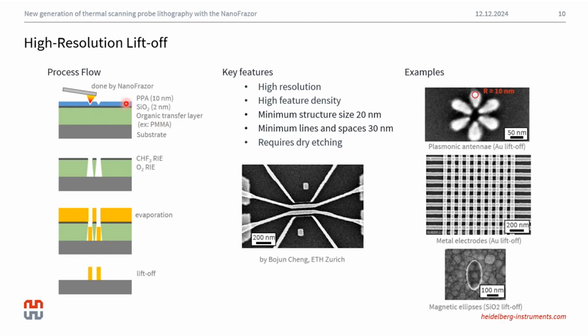Once your stack is created, we again launch the patterning by writing on the top PPA layer. In this case, we apply a series of dry etching steps using a reactive ion etcher, RIE, to transfer the patterns downwards. Then we use a directional deposition method, in most cases evaporation, to deposit material on our samples, and again we lift off the entire stack, again either with acetone or DMSO, depending on the organic transfer layer used. And for all these etching recipes, we've combined our know-how over the years in a recipe book that we offer our customers.